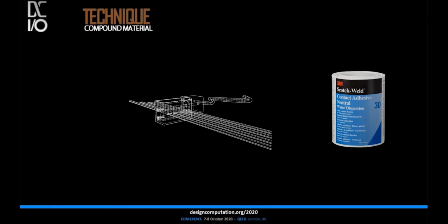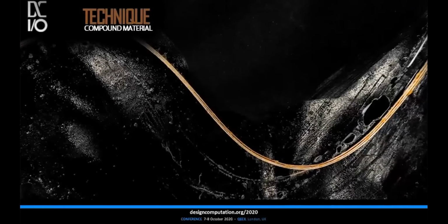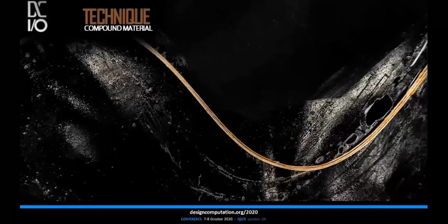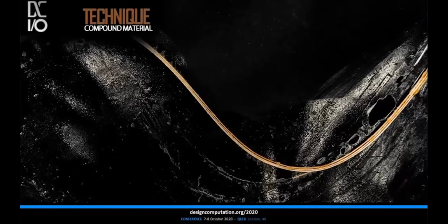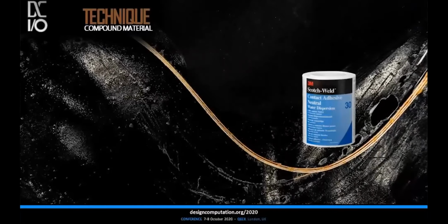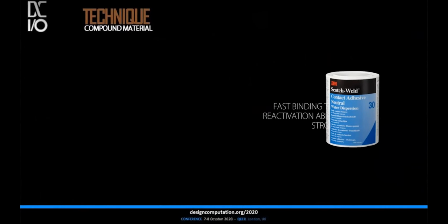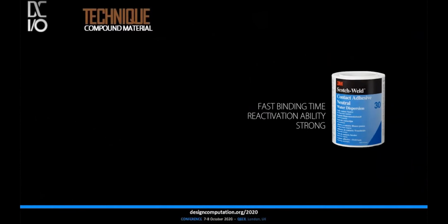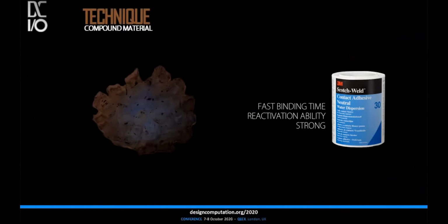The laminated and dry strings are then reactivated by applying heat at a temperature of around 50 degrees Celsius. By pressing the single filament strips together, a combined square extrusion can be produced. This adhesive is currently fitting our manufacturing and parameter constraints. Other gluten-based glues share the same characteristics and could also be investigated due to their reusable and sustainable characteristics that fit the overall goal of this research.